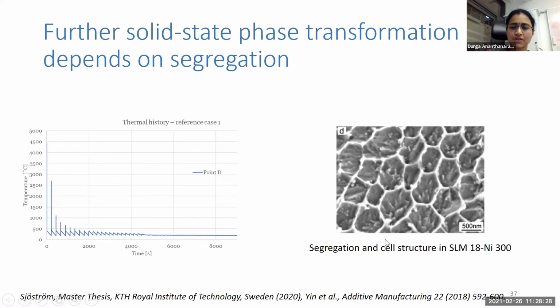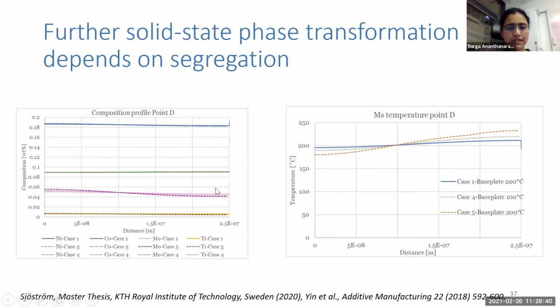Similar to this tool steel, we also had martensitic transformation happening, and the final structure only had martensite and some retained austenite in the intercellular region. She did segregation calculations using Dictra this time, and found that you have some level of segregation for certain elements like molybdenum and titanium. We also know that the martensite start temperature depends on the composition. This shows the intercellular region, and this is the middle of the cell itself. In this range, the martensite temperature would also vary depending on the composition.